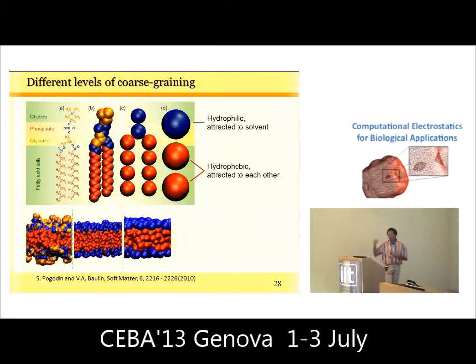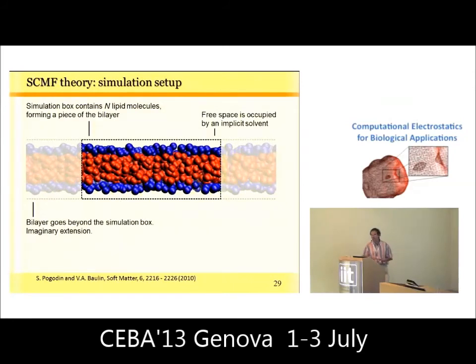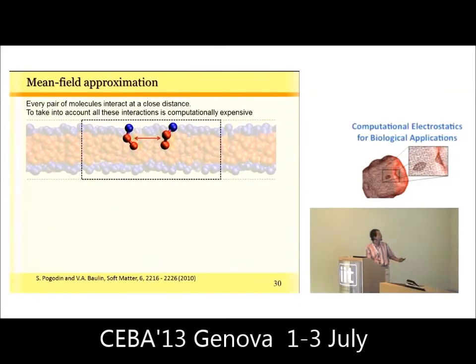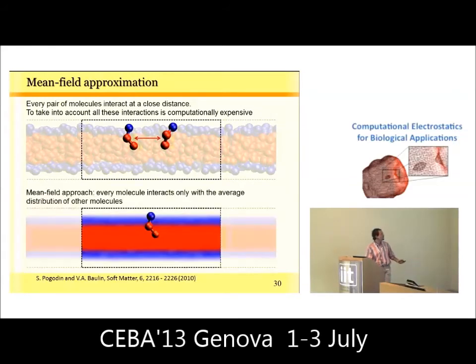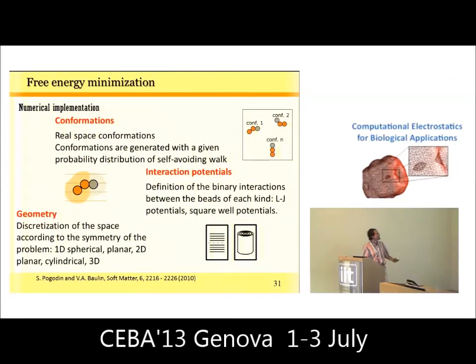And when we calculate the fields, we can get self-assembled structures like this, and the parameters of this model can reproduce the real experimental data for phospholipid bilayers. Instead of calculating interactions between the molecules, we just calculate the interaction with the field.